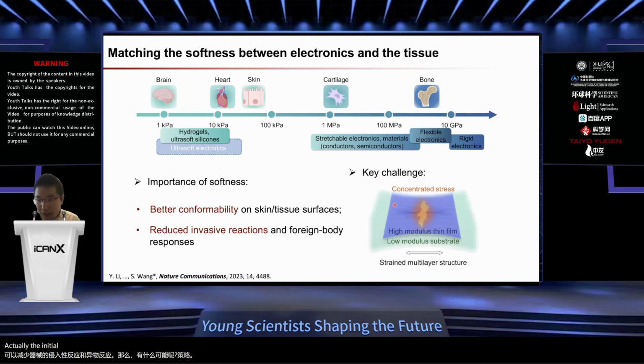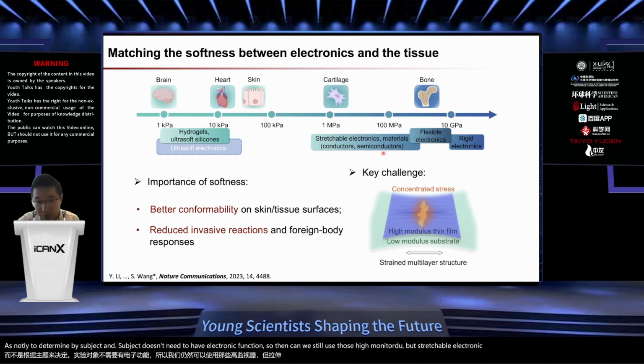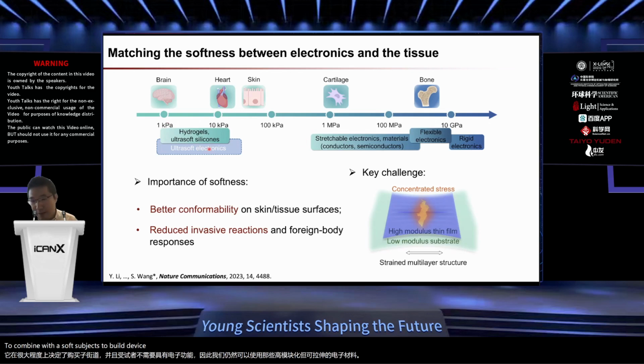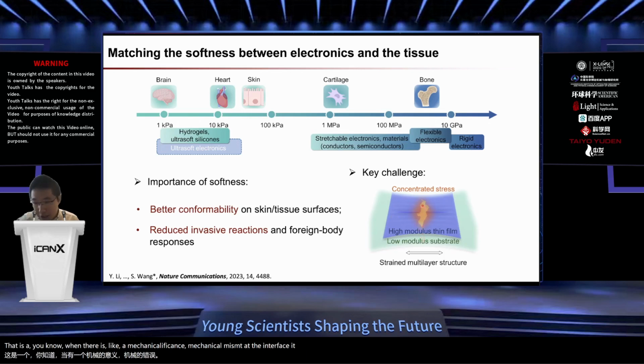Actually, the initial thing we started to think about is that this is probably a pretty simple challenge to solve, because the overall mechanical property of a device is largely determined by its substrate, and the substrate doesn't need to have electronic function. So then, can we still use those high modulus but stretchable electronic materials and combine them with soft substrates to build devices? When we started to do some very simple tests, we found there is a very major challenge. When there is a significant mechanical mismatch at the interface, it usually leads to significant concentration of stress. That leads to a large decrease of the stretchability of the supported high modulus film.